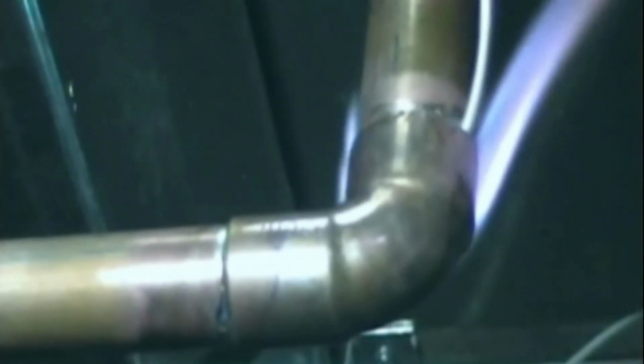Oh my God. So when the instructor emphasizes the wire brushes and the emery cloth, he is not telling you to polish the pipe. He's telling you to perform a brutal physical excavation. That's exactly it. You are tearing away the reacted atoms to expose the virgin, unreacted copper lattice underneath. Just ripping it down to the raw material. And by scratching the surface with the abrasive cloth, you are also dramatically increasing the microscopic surface area. Because of all the little gouges from the sandpaper. Right. It provides thousands of tiny physical ridges for the liquid metal to bite into.